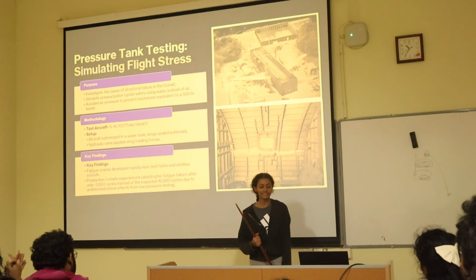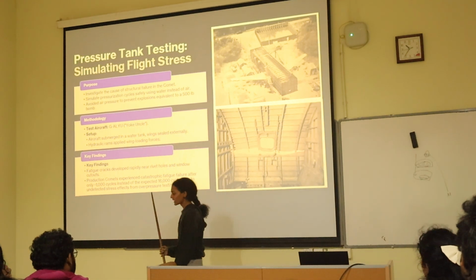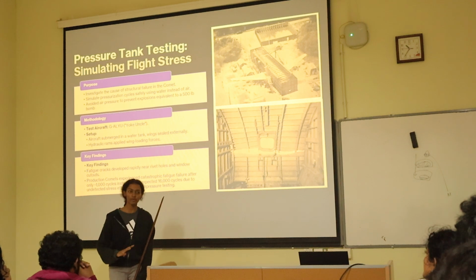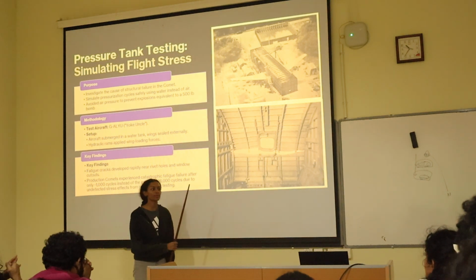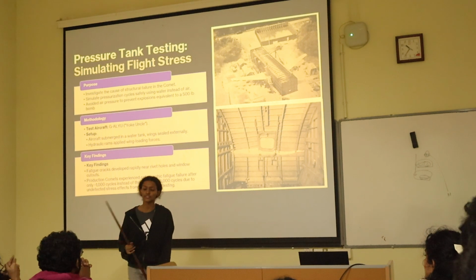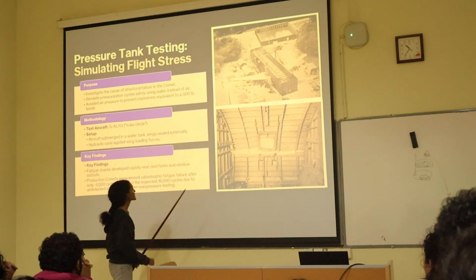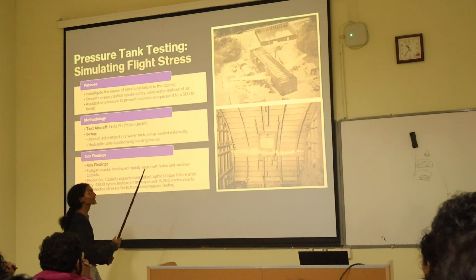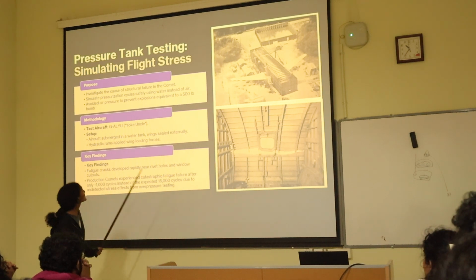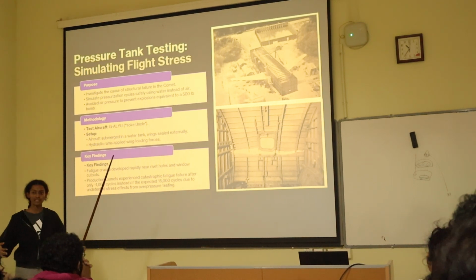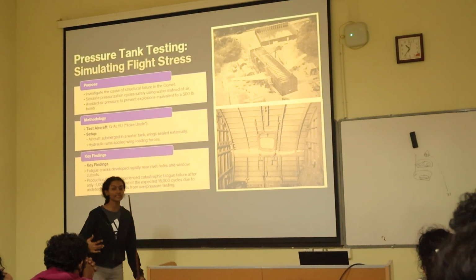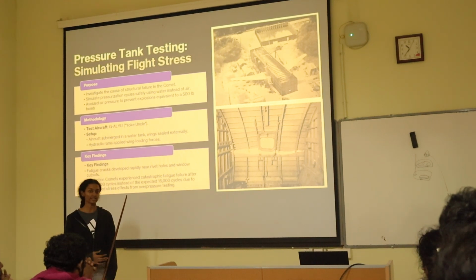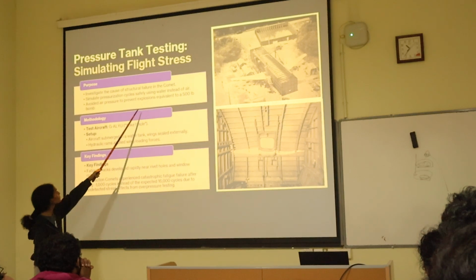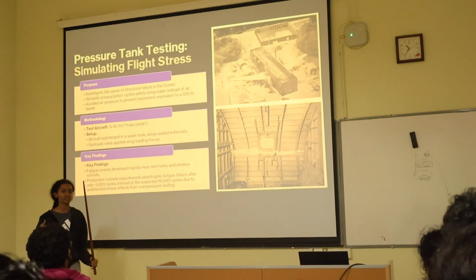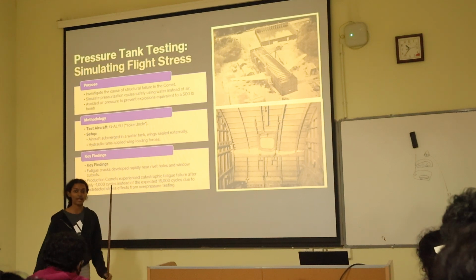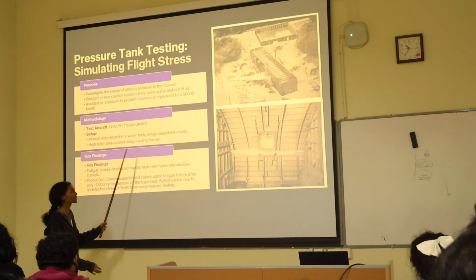Yeah, so the pressure tank testing. When the Comets failed, after the first two were explained by weather conditions, for the last two, their license got cancelled, and after that they did pressure tank testing. In this testing, they placed the fuselage in a water tank. The reason was that this reduced the amount of destruction, as we don't want an explosion to happen. So to moderate that, it happened in a water tank.